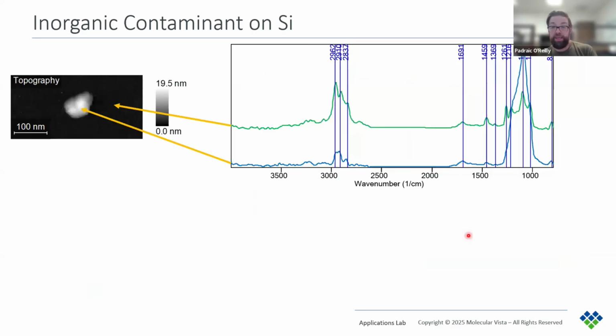So not only can PiFM ID organic contaminants, but also inorganics. In this example, we have a particle on a silicon wafer. The green spectrum is taken on the substrate, and the blue spectrum is taken on the contaminants. Interestingly, the wafer also has a very thin layer of contamination too.